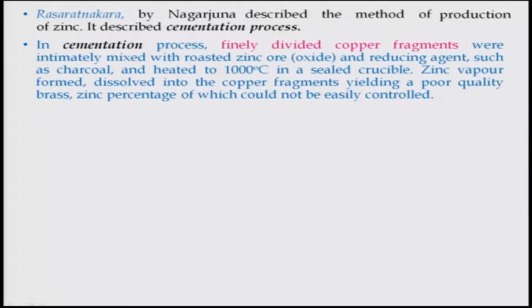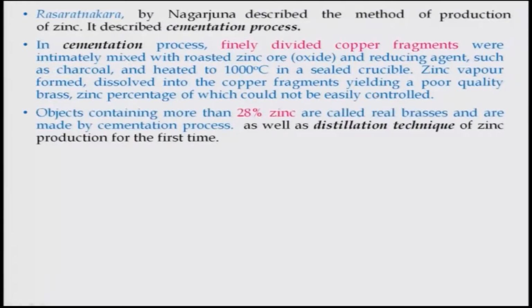And in this cementation process, finely divided copper fragments were intimately mixed with the roasted zinc ore and reducing agents such as charcoal, and heated up to a temperature of around 1000 degrees Celsius in a sealed crucible, and the zinc vapor formed dissolved into the copper fragments, yielding a poor quality brass. And unfortunately, by this method the zinc percentage could not be easily controlled, but they produced this brass in small quantities because it was for medicinal purposes. And objects containing more than 28% zinc are called real brasses, and were made by the cementation process, as well as the distillation technique of zinc production for the first time.